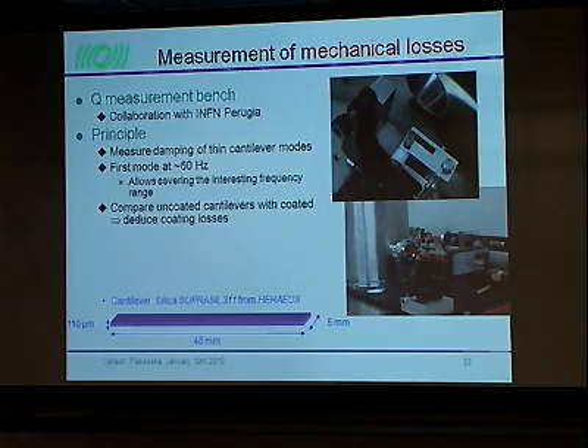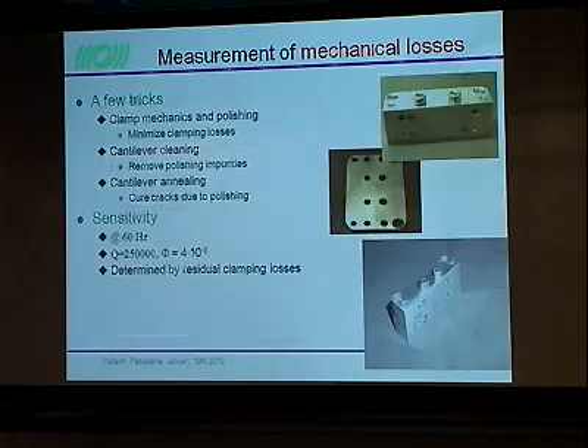One thing that we pay attention to is to have the geometry such that these cantilevers have modes in the region of interest. So for example, we use cantilevers which have first mode at 60 Hz so that we can have a measurement of the losses at the right frequency. We believe this is something important since we know that some of these loss mechanisms can depend upon the frequency. This system is able to measure Q as high as 250,000 at 60 Hz, which is sufficient to study the coating losses of both high index and low index material.